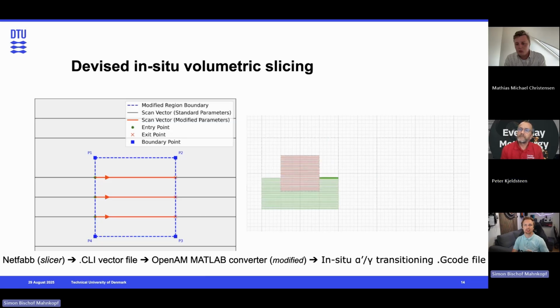Yeah, so quickly, you mentioned the martensite start temperature. And that's the thing about this process, because we have a very small cell structure when doing 3D printing, the martensite start temperature, we actually suppress it so much that it's not really a concern here. We don't actually get any thermal martensite. We only get strain-induced martensite. But the strain-induced martensite is coming from thermal strain. So that's how we're actually using the thermals to create strain-induced martensite and not thermal martensite. So the higher the start temperature you have, the more extreme the cooling will be, and therefore we get a higher strain.